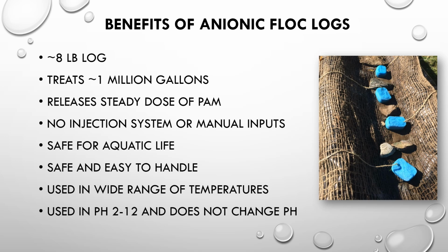It's important to note that temperature does matter. If the water is very cold, like most things, if we heat water up, we can dissolve things faster in it. So if the water's colder, the polymer is going to dissolve a little bit slower. So we might need more reaction time to form those flocks. We also might need to put more logs in to start because we're not increasing the dosage. If I have 4 flock logs and they dissolve at a certain rate, now if I cut that dissolution rate in half and they're dissolving 50% slower, then I need to add 4 more of them just to get up to the same dosage. So we might use more logs in colder temperatures, not to increase the dosage, but to keep the same dosage.